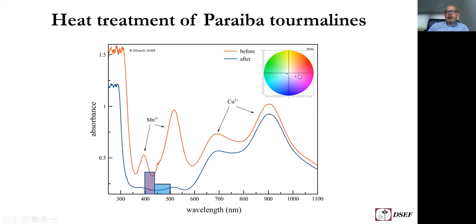This is the corresponding plot point in the color circle. And if you heat treat the stone, you actually reduce the manganese bands, both bands here, leaving behind a transmission maximum here in the blue to green part of the visible spectrum. So by heat treatment, you can produce this color from this color as a result of reducing the manganese.